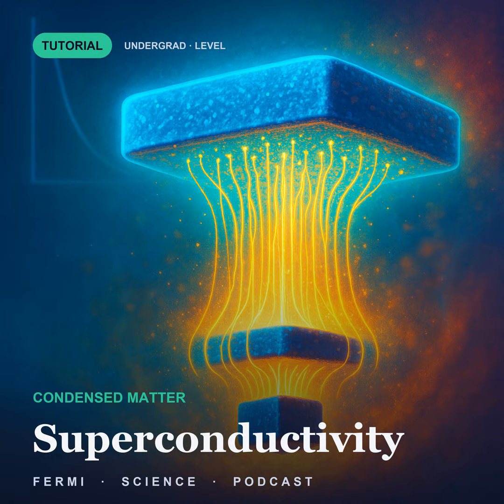Hydrogen squeezed to 1 million atmospheres does beat that on phonons alone. A cuprate has no such mode in it. The parent compounds are insulators, but not band insulators. They have a half-filled band and would be metals if the electrons ignored each other, and they insulate because of the repulsion between them, so the Fermi sea Cooper's argument starts from is not there to be destabilized.